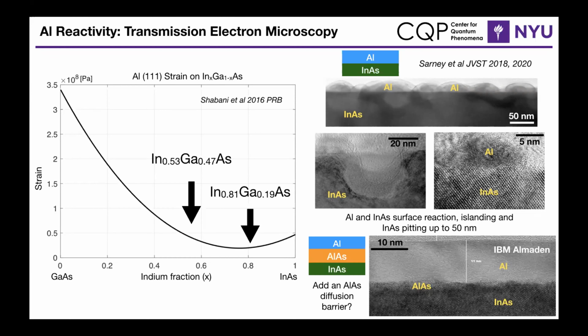So what was found in this paper and what we showed was that you can actually introduce an intermediate aluminum arsenide layer that will limit the diffusion between the aluminum and indium arsenide. And as you can see in this TEM image, we're able to get nice epitaxial aluminum sitting well over indium arsenide with this aluminum arsenide in between.